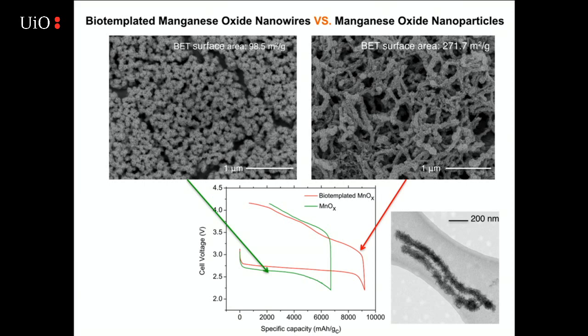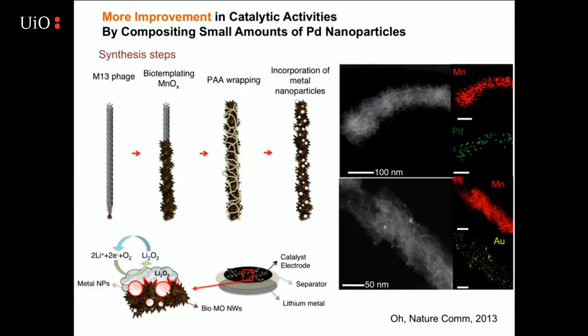They actually have this very spiky structure. This is actually just precipitating these materials, and this is grown biologically. You can see the surface area is greatly increased by this. This is looking at some initial data for our biotemplated versus our deposited manganese oxide-based material. All of these, of course, are made at room temperature. Then what we decided to do was to add a little bit of another element, either gold or palladium, to these structures. You can either do it through biological means, or you can do it through adding a little bit of a polymer that can attract these nanoparticles.